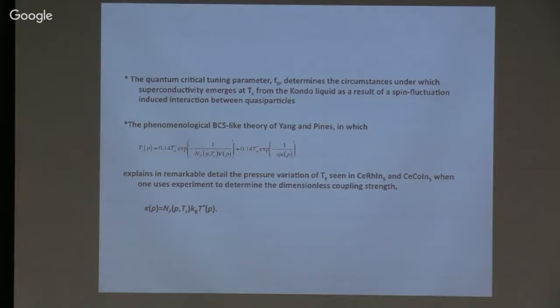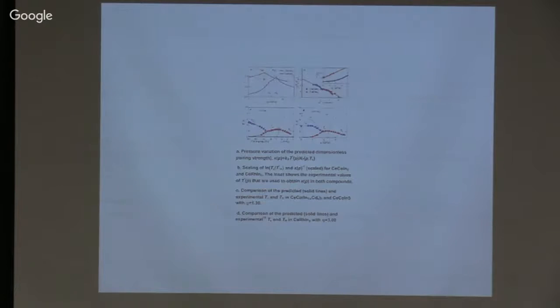And you have a simple expression like that, and that actually explains the variation of TC that you see in both the rhodium-115 and the cobalt-115. That's the dimensionless coupling strength. Here's a picture of how well we were able to do. So in the top left, you see the dimensionless parameter that I mentioned. The top right shows the way in which these materials are behaving as a function of doping or pressure, and then the predictions of our theory, phenomenological to be sure, for the Néel temperature and the superconducting temperature are shown in the bottom left and the bottom right. And it's pretty amazing that with a tiny set of parameters, most of them obtained from experiment, you can nail the variation in TC that you see experimentally for these materials.